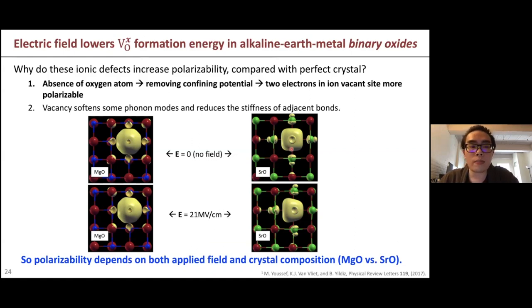Because we don't have the oxygen atom anymore, those two electrons remain, which is the definition of a neutral oxygen vacancy: the oxygen leaves without taking away the electrons, so everything stays neutral.